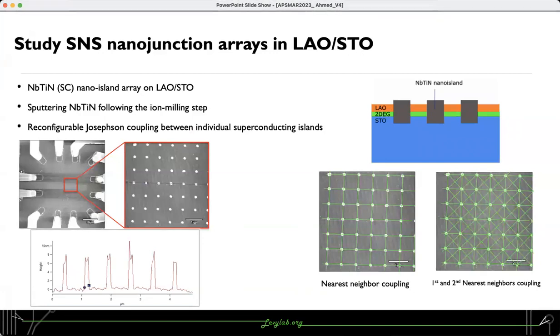In this direction, we place a superconducting material, namely niobium titanium nitride, which has bulk Tc of 15 Kelvin, inside the nanovias. This is done using sputtering following the ion milling step. The idea here is that we can create reconfigurable links between the individual superconducting nanoislands on the same device. By doing this, we can study the effect of changing the Josephson coupling on the transport behavior of the superconducting array on the same sample.